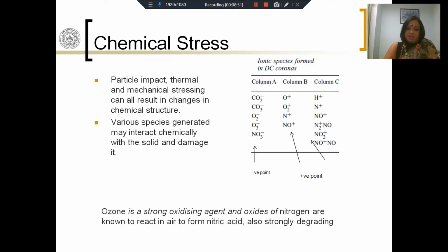Then we have chemical stresses. Particle impact, thermal stresses, and mechanical stresses can all result in changes in the chemical structure. Various species may be generated, and these species may interact chemically with the solid and cause damage to the solid material. For example, if you look at ionic species that might be formed during DC coronas, in column A, you have byproducts which are created when the point electrode is negatively charged. So you have CO2 negative ions, CO3 negative ions, O2 negative ions, O3 negative ions, NO3 negative ions. When the point is positively charged, you can have O positive, O2 positive, nitrogen positive, nitrous oxide positive. You can have hydrogen positive, nitrogen positive, NO positive, N2 positive, NO positive, NO2 positive.